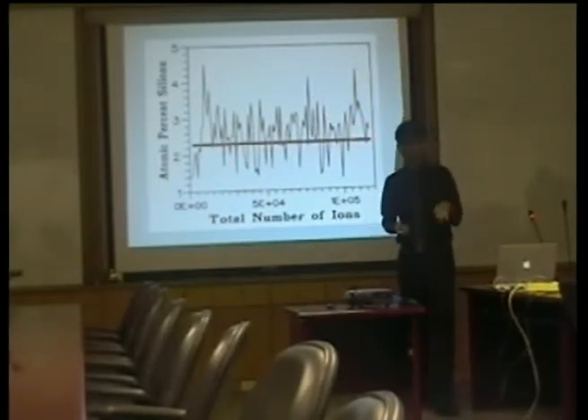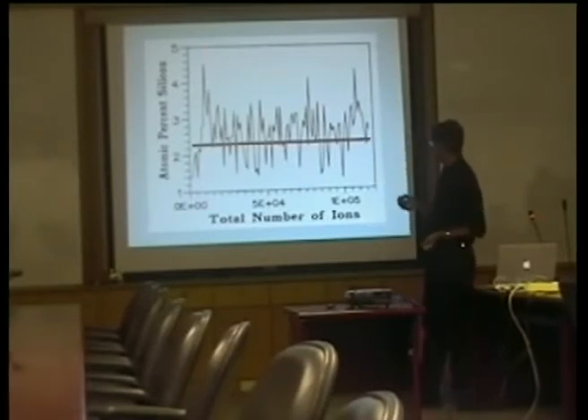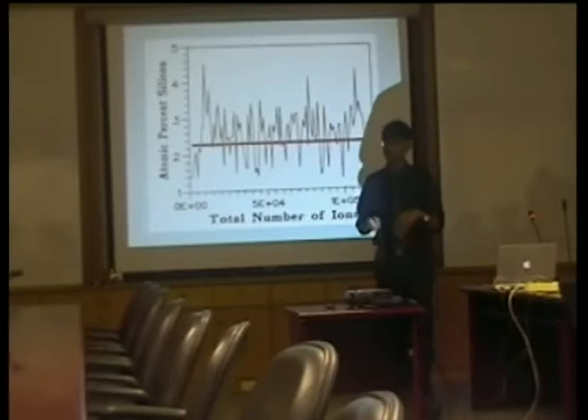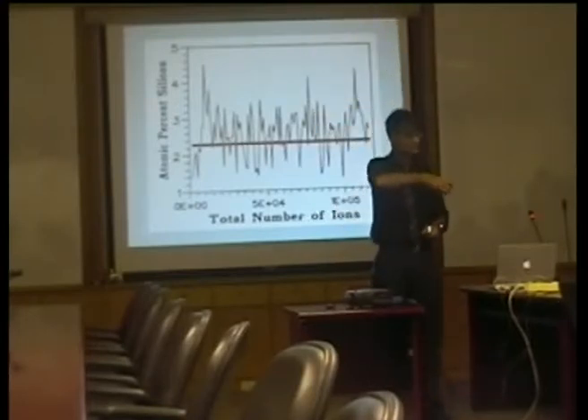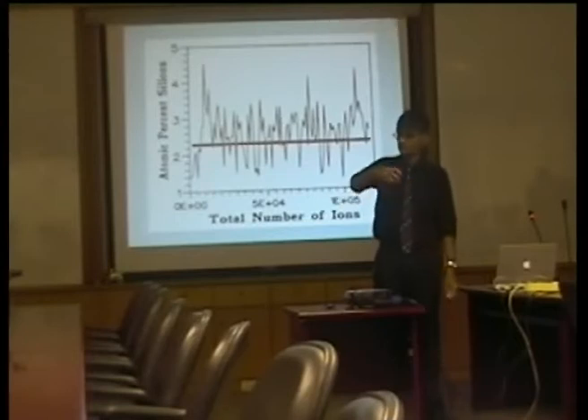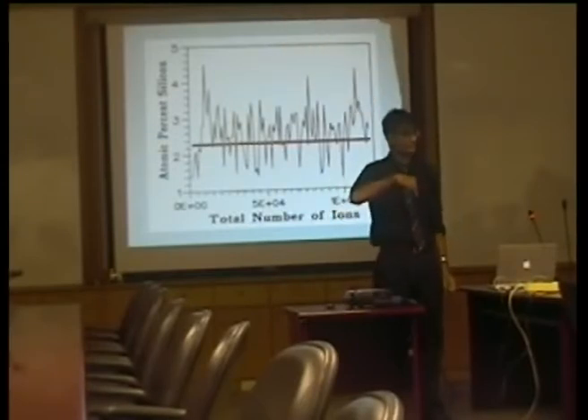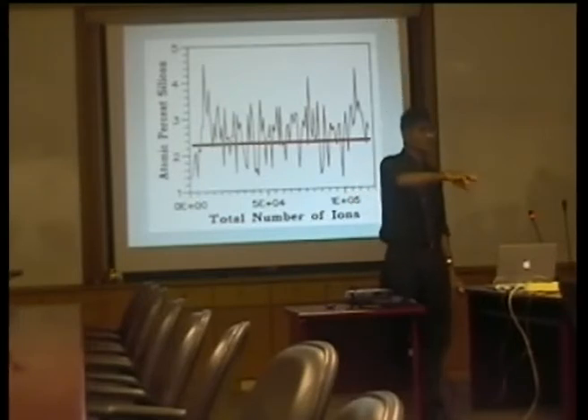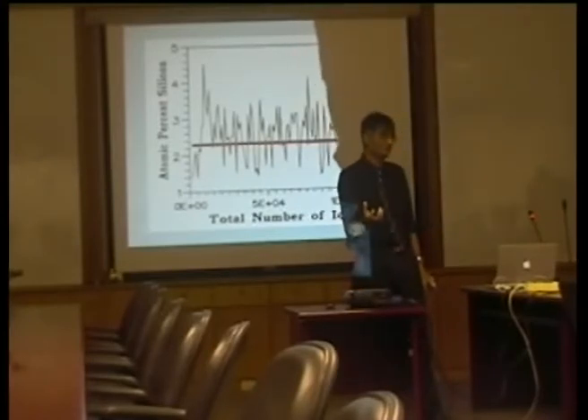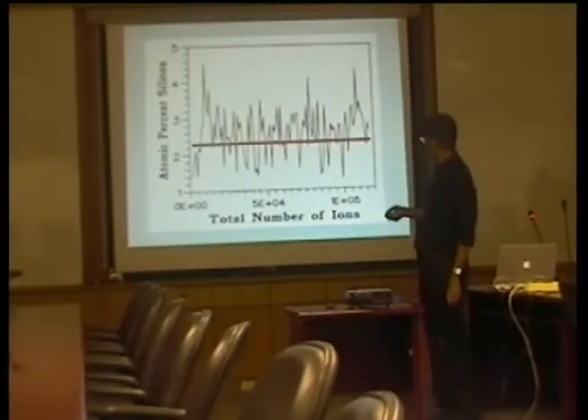Here I'm plotting the concentration of silicon in the material, and you know, it shows these variations, but those variations are not real. There are variations because we are picking out small numbers of atoms. Yeah, so if I pick out just 50 atoms, then the composition of that will be different from the next 50 atoms. It's just like you've got elections going on at the moment. Yeah? If you go and pick out 5 people, they might all be voting for one party, and you might say, okay, 100% of the population is going to vote for this party. That's not correct. Yeah? We have to take account of statistics. So these variations are not important. We can show that the material is homogeneous by showing that the variations follow a binomial distribution.